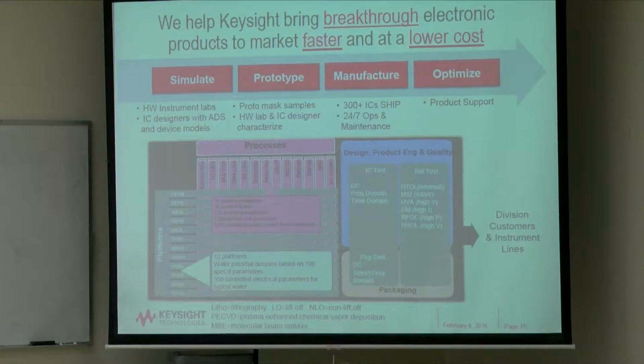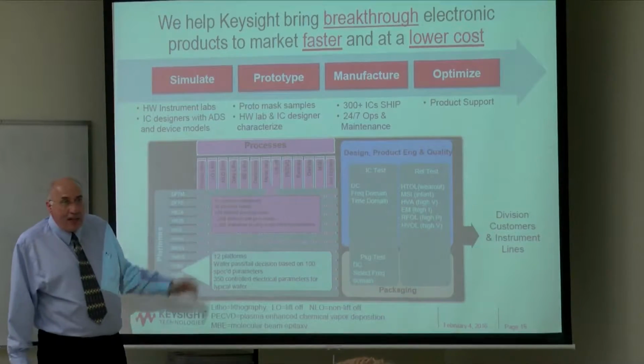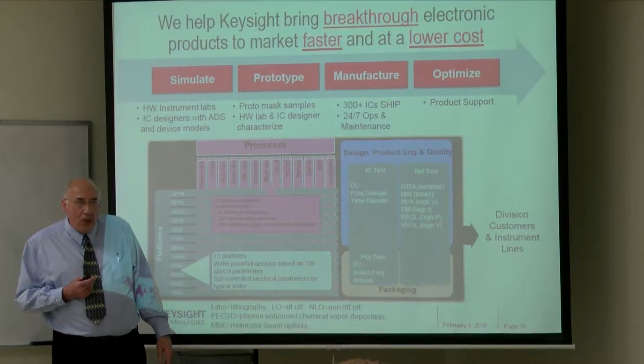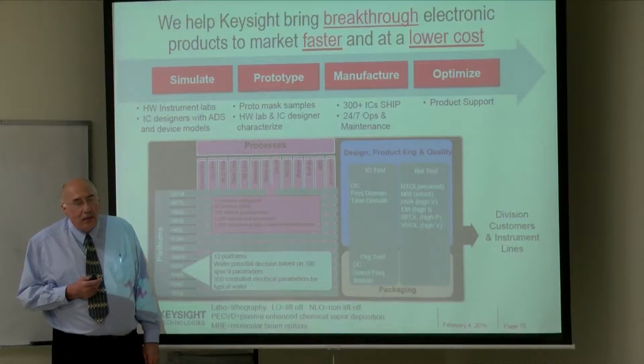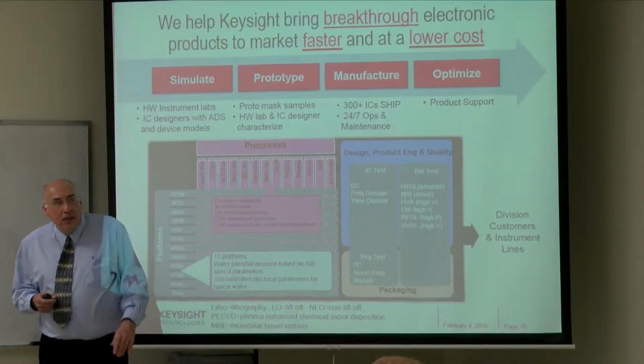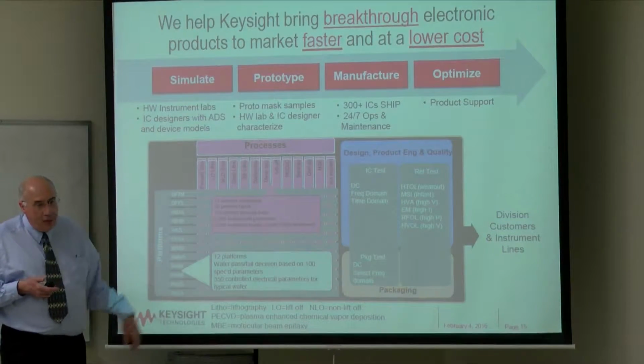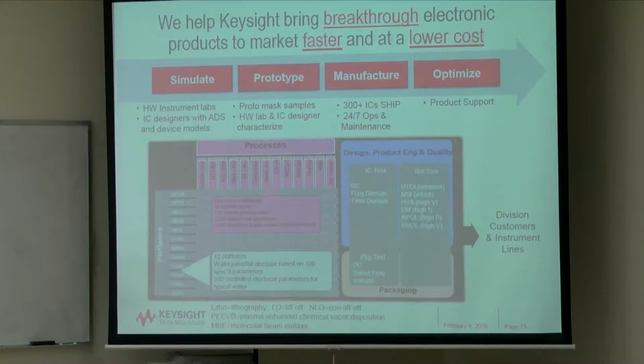And the reliability testing, even as you see from this flow, it takes place at the worst possible time. You've spent all the months to do these process steps. You've done all this IC characterization, and then you pull a few test arrays off the wafer and subject them to some of these reliability screens, and it fails. And all of that effort is for naught. And one of the vice presidents said, well, wouldn't it be smarter to do your reliability test back here somewhere? And the answer is, if we knew what to do back there, we would, but we don't. You've actually got to go through the entire fabrication and then test samples from each wafer. And we've been doing this for a long time. Some of them are on an audit basis where you just do it every month. Some, to this day, every single wafer we produce, you do reliability.